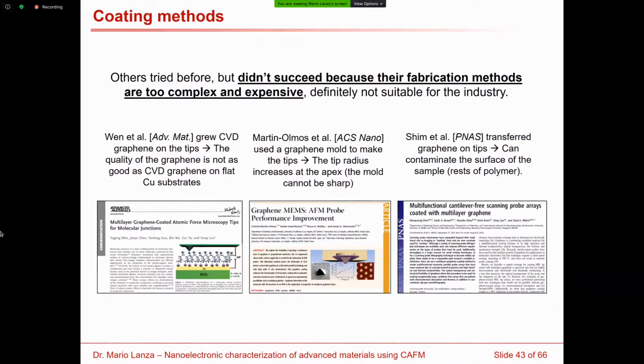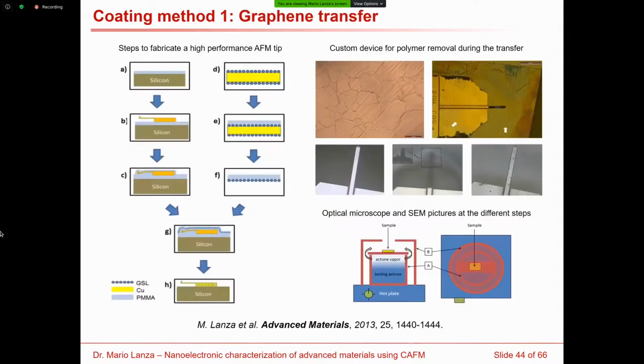And the last method was the transfer. It was not really used on tips. It was used on kind of pyramidal samples. So we were the first group to try this on real tips. Basically, first we fix the tip onto a silicon substrate, and then we prepare a flake of graphene, a sheet of graphene covered with PMMA, and we transfer it onto this tip that was fixed. Here you can see all the stages of this process.